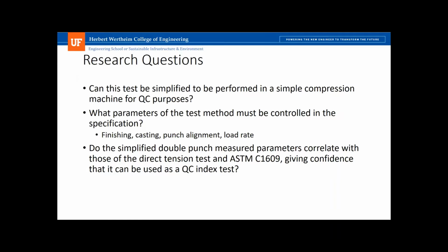The next thing we wanted to look at is what are the parameters of the test that you have to control and specify that are going to cause issues. So we wanted to look at finishing process. Do you have to grind these samples flush, or can you just trowel them? That makes a big difference in sample prep for labs. How to cast them. That was an issue we wanted to look at. Punch alignment, if you're off a little bit with the punches, does it make a difference? And the load rate, especially the load rate, because the load rate on a lot of these machines is a little bit harder to control. You don't get a dialed in exact 1 millimeter per minute displacement.